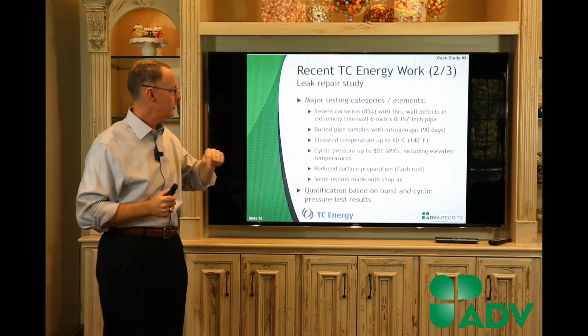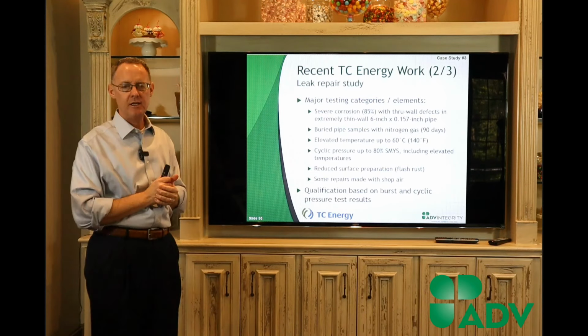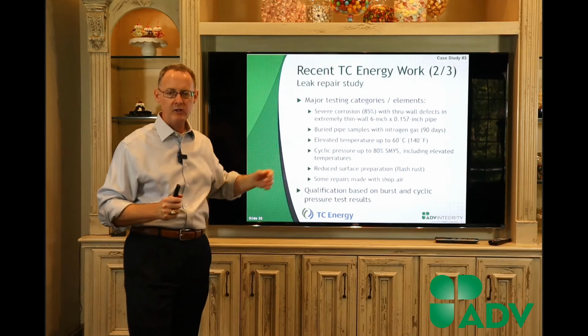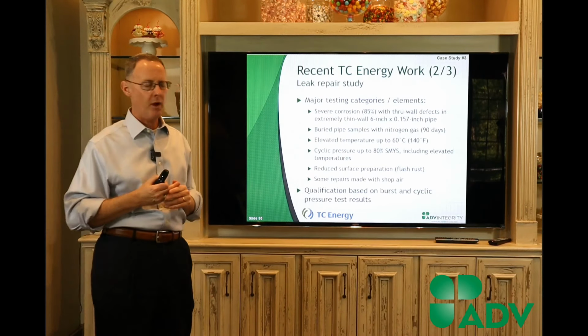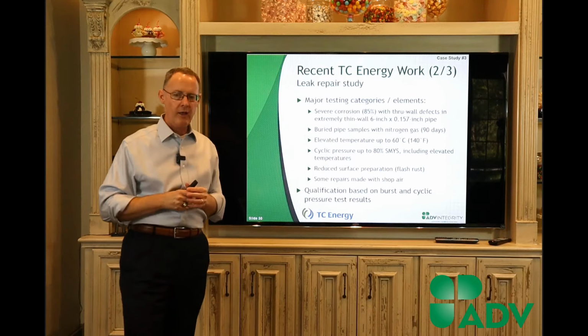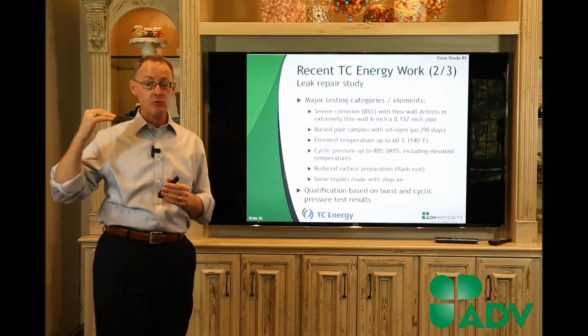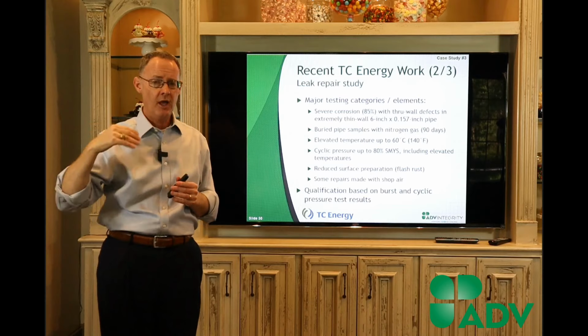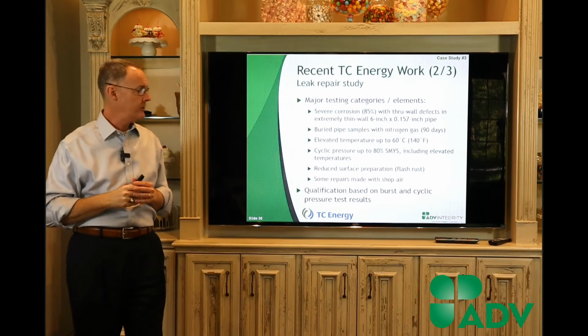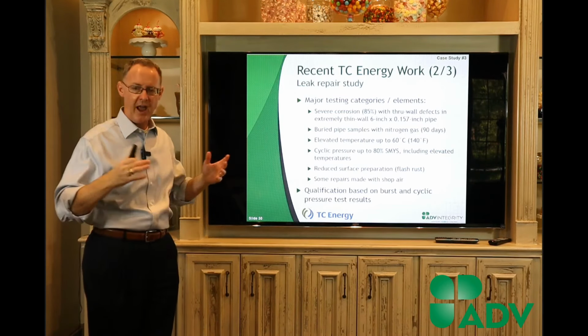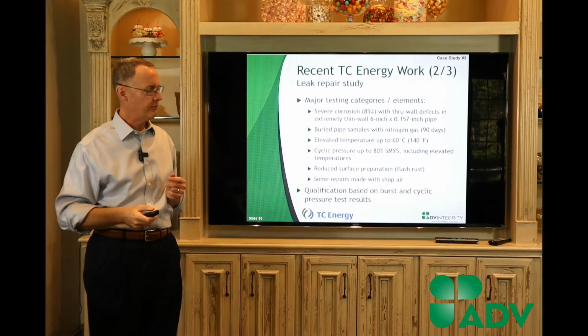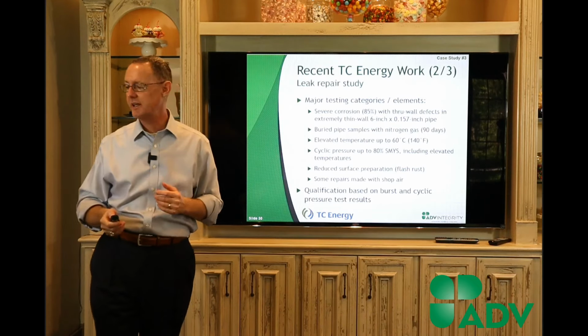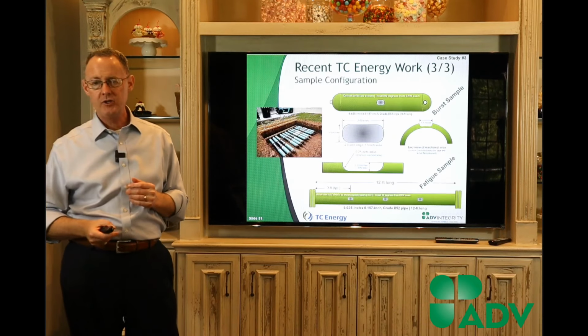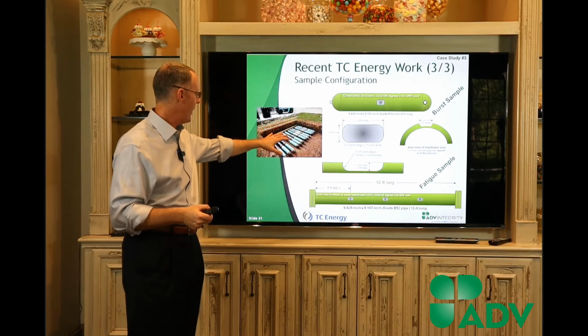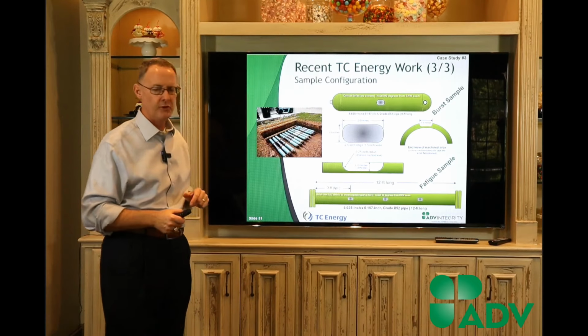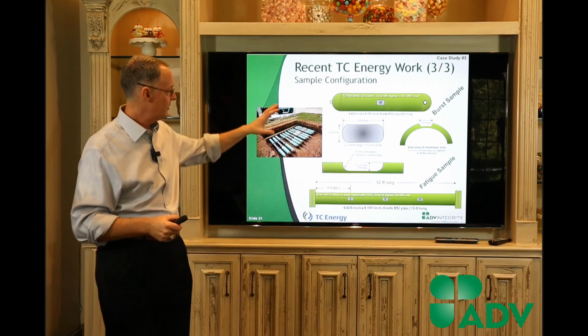And so some of those we drilled holes in them. We did nitrogen gas testing for 90 days. We did some elevated temperature testing just to simulate how these composite systems would perform. The Canadians run to a higher pressure than we do for the most part, so they run up to 80%. So we really pushed the limit on these technologies. We also looked at flash rust and not having ideal surface prep. And we did burst testing and cyclic testing. And these are just a couple of images. This is the buried pipe in the ground before we put the soil back on. And these are just some schematics.